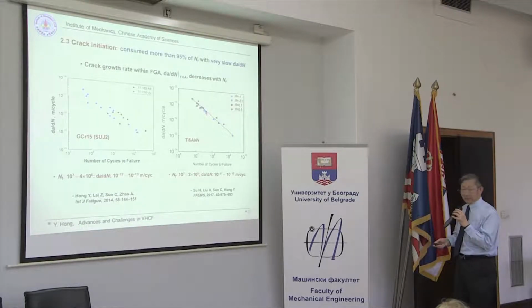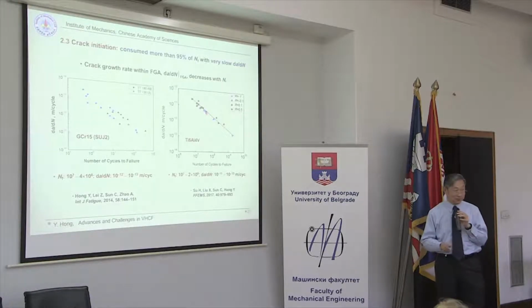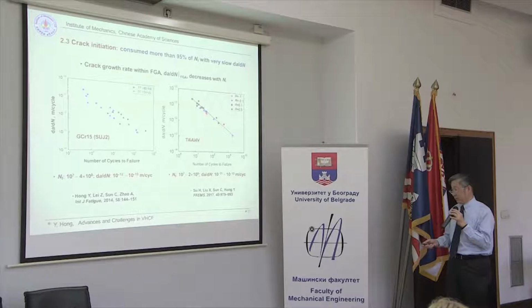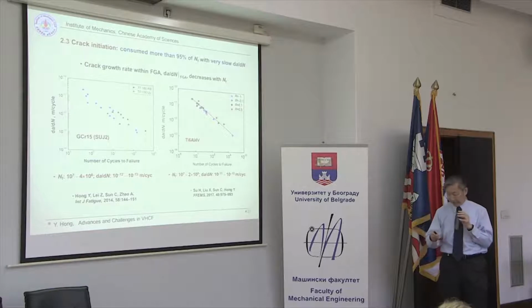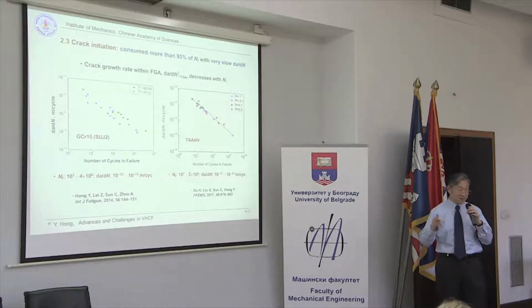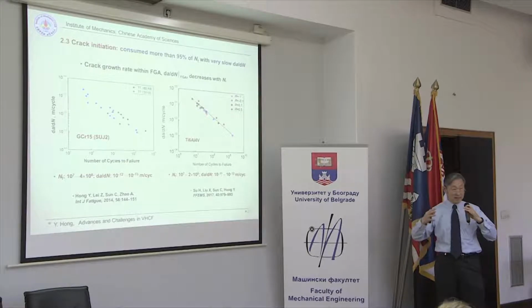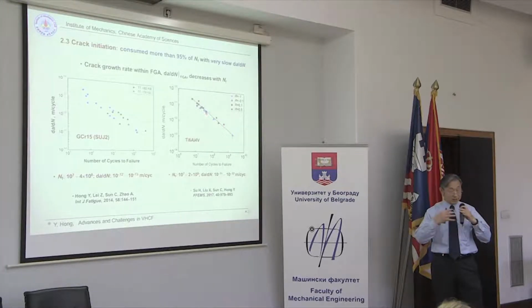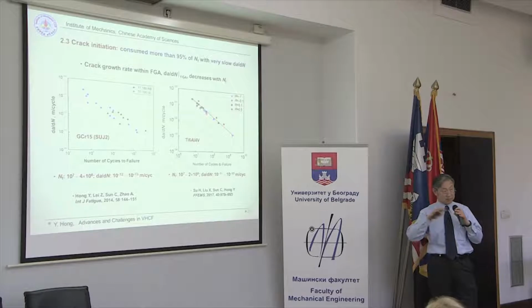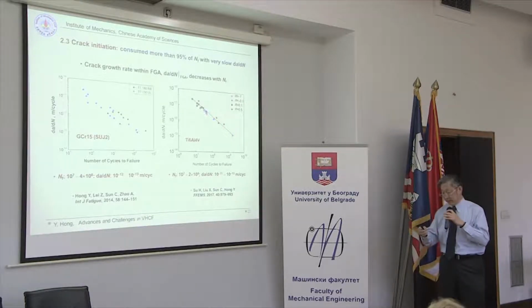This is an example for high-strength steel and for titanium alloy. And we notice that the rate is so slow for high-strength steels, 10 to the minus 12 and 10 to the minus 13 meters per cycle, and for titanium alloys, very, very slow. These data are connected with the previous result, that the initiation life is almost a dominant part of the fatigue life.